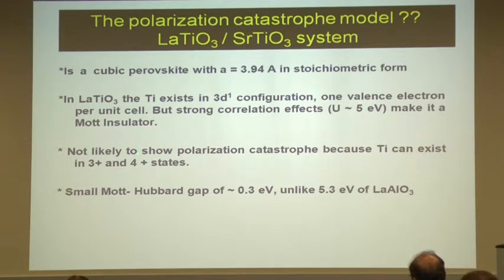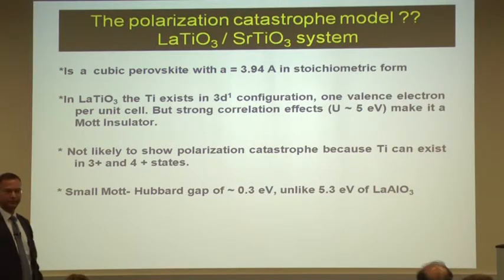It is not likely to show the polarization catastrophe because titanium can exist in 3+ and 4+ states. So this is the difference between aluminum and titanium. Aluminum, the valence is fixed, 3+. Here it can be 3+ and 4+. And the Mott-Hubbard gap is very small, 0.3 electron volt, whereas the band gap in lanthanum aluminate is 5.3. So these are two different beasts altogether. And we will try to show you that whatever manifestations are, they are actually the same.